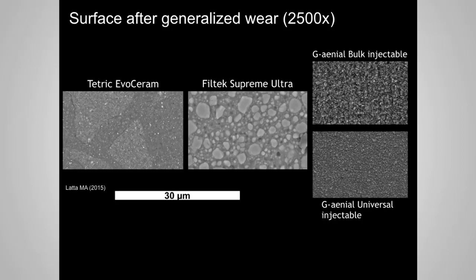So here's what we're talking about with the surface after generalized wear. This is from the EvoCeram, which is the Ivoclar product, and this is Filtek Supreme after the wear. You see all these spaces in between, and when you see these injectable materials, you see very little wear after 2,500 times the wear. So it really matches up to these other materials very, very well.